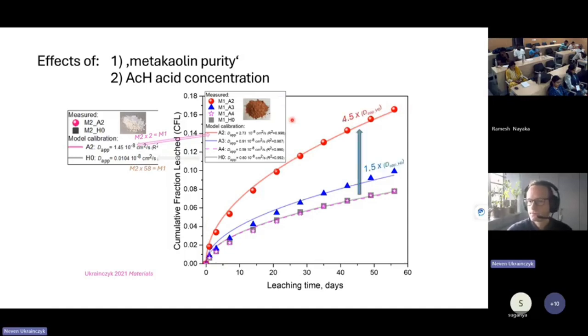You could see that this is almost 5 times increased apparent diffusion coefficient. As I told you, we can model it with a simple diffusion equation. And with the white clay, those diffusion coefficients were actually two times or even 58 times lower. So actually these performed better. And this again we can explain by the fact that here we have a bigger amount of geopolymers than here. But the problem with this is that this mixture cracks. It has very high dry shrinkage sensitivity, and this one doesn't crack.